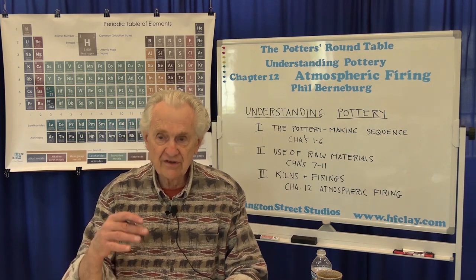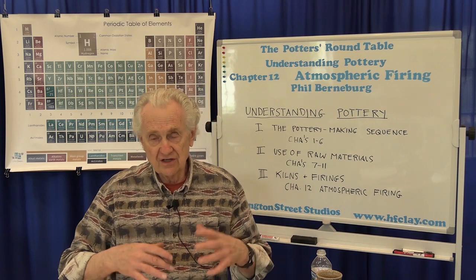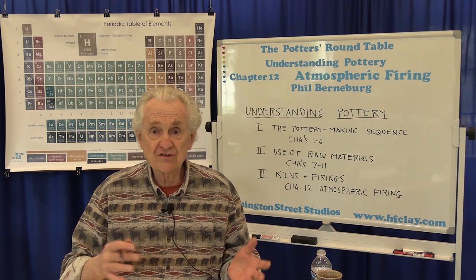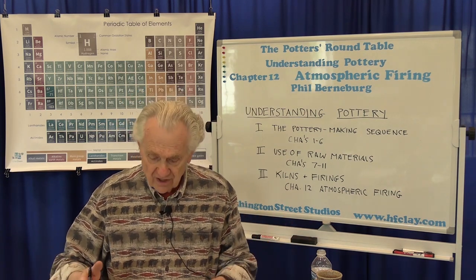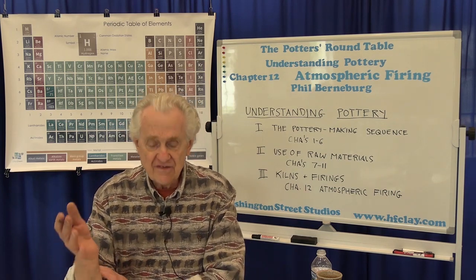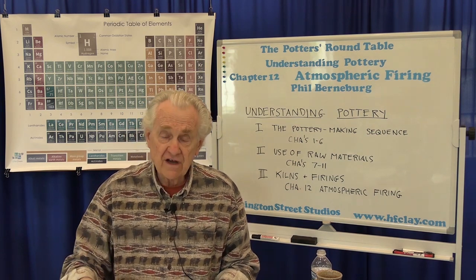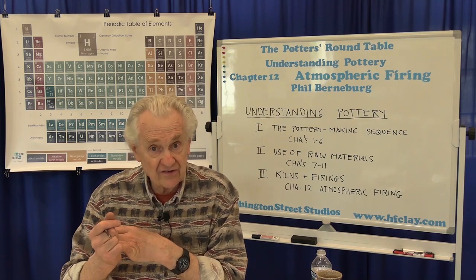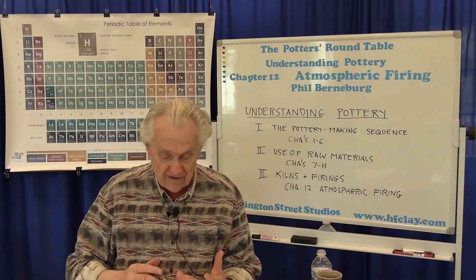The nice thing about these materials is that the only byproducts — instead of chlorine — are carbon dioxide and water, the same as from the burning of the fuel. So you've eliminated the chlorine pollution. You get basically the same effects from the sodium vapor in soda firing that you do from salt firing. There's a fluxing action on clay and glazes, there's a bleaching of glazes, and you could also get the crazing effect.